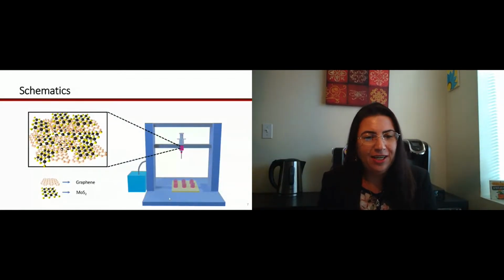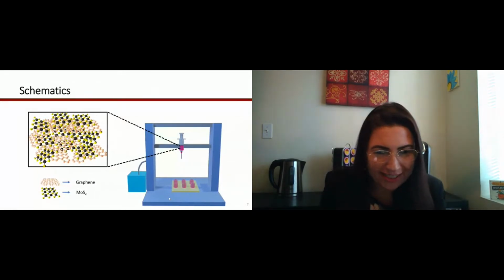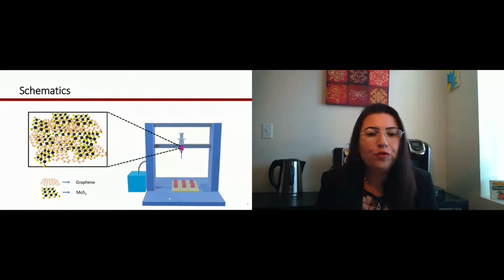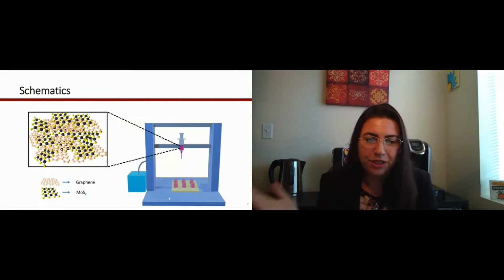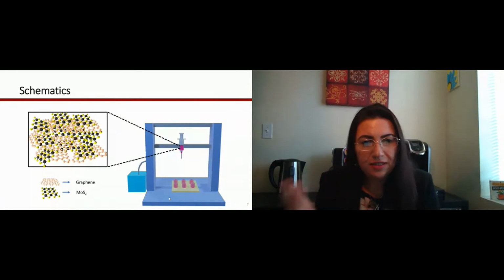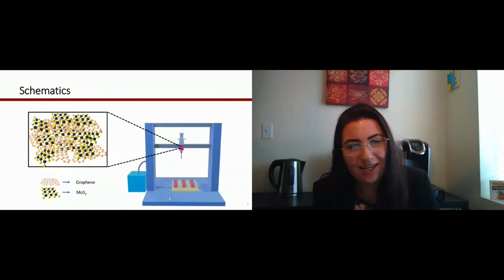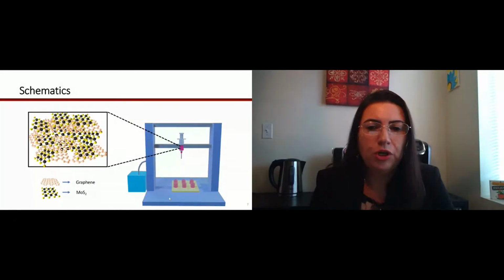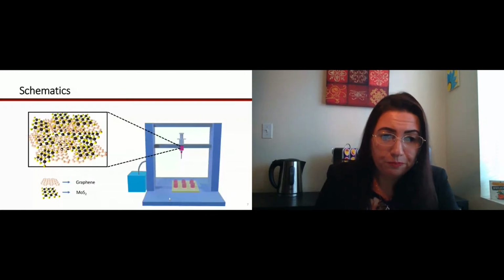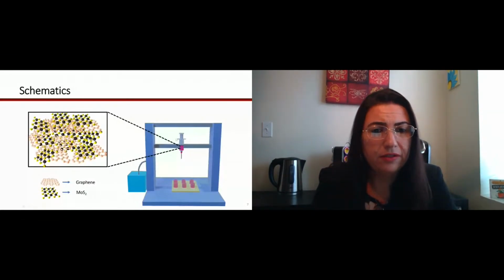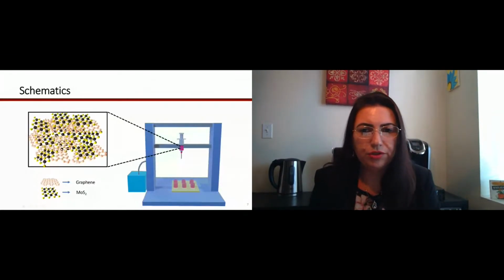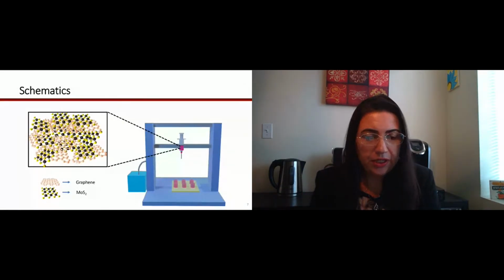We didn't have any of that. We didn't have money for that either. And part of Grow was they could pay for me to go to France, to a professor there. He modified the 3D printer to 3D print with a syringe. So we made the gel, we mixed the graphene and MoS2, and we 3D printed that, and after we did lyophilization.